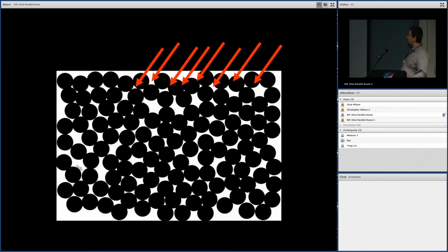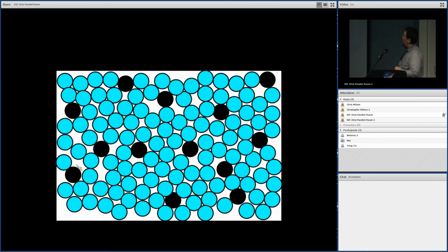If we have a strong absorber and we shine some light on it, we would expect that the top layer of the sample, these packed particles, is all that's interacting with the system. Any reflections that you get off the surface are coming from that upper layer, maybe 1 or 2 particles deep, maybe a little bit more, but not much. You're not penetrating deeply into the sample.